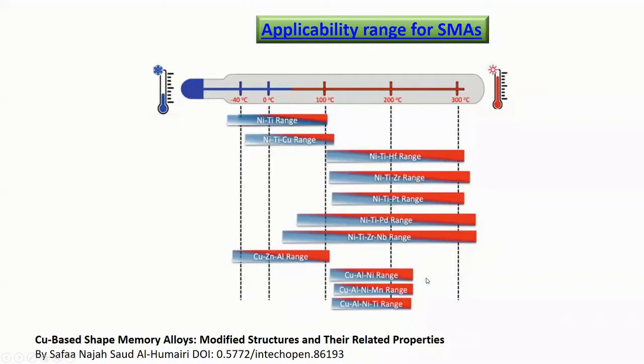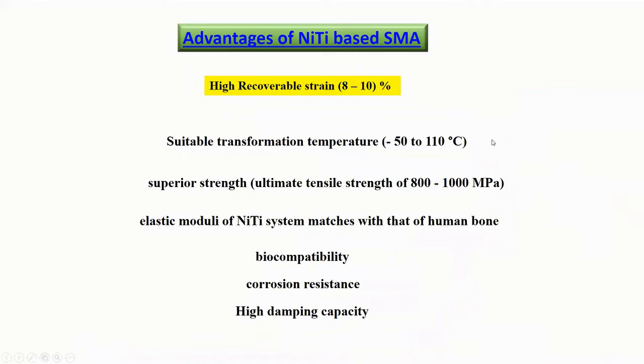Okay, so based on all these different kind of properties and the temperature range, we have seen that nickel titanium somehow survives as the best material, which is having the highest recoverable strain of around 8 to 10%, quite high compared to any other standard metallic system. And it has a suitable transformation temperature, whereas superior strength and elastic moduli, which matches with that of the human bone. So that is why it is being used as implants in many cases. It is also biocompatible. So that is another important property of nickel titanium, which has made it an important candidate for biomedical application. Plus, it is corrosion resistant. It has very good corrosion resistance, and it has a quite high damping capacity.